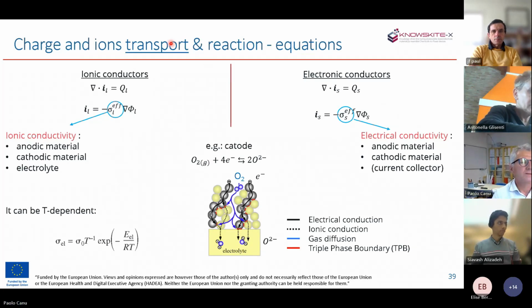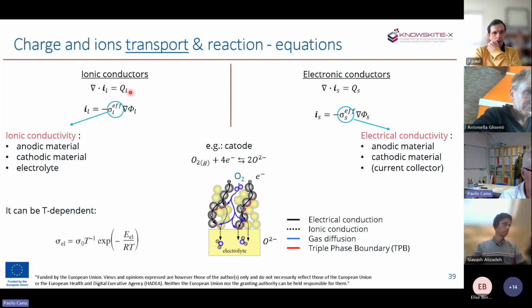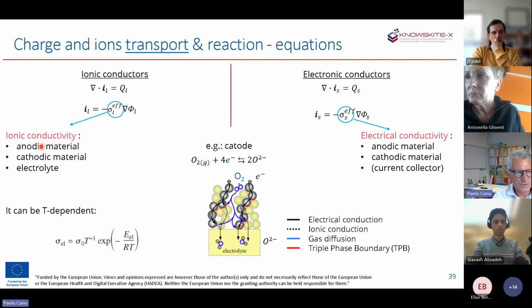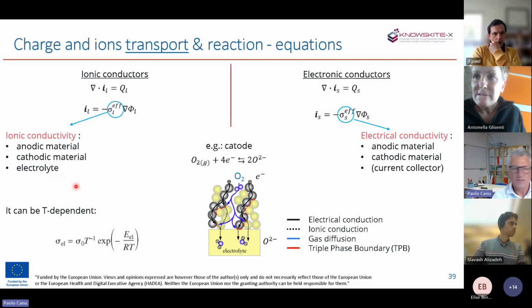Quantitatively, in terms of equations, the transport of charged species involves, at steady state, a balance that says that the flux of ionic species is equal to the production or consumption. And the flux is ruled by the ionic conductivity multiplied by the gradient of potential. This ionic conductivity must be determined across the anodic electrode, the anode, the cathode, and the electrolyte. All these properties are quite difficult to measure, and they strongly determine the output of the simulation. They can also change locally as a function of temperature and the local potential.